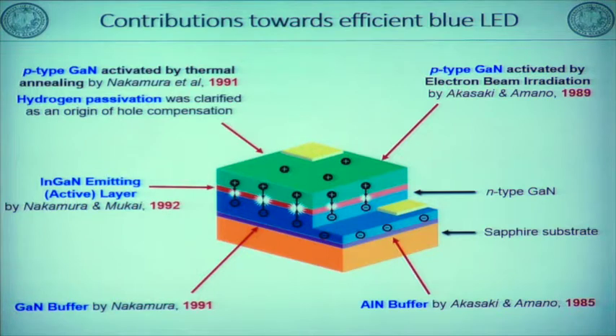P-type gallium nitride was achieved by electron beam irradiation by Professor Akasaki and Amano in '89, for the first time. That's the reason they got the Nobel Prize, because at that time nobody could get P-type gallium nitride. In my case, I developed P-type by using thermal annealing. Also, I clarified the mechanism of why we got P-type gallium nitride by annealing and electron beam irradiation. It's caused by hydrogen passivation.